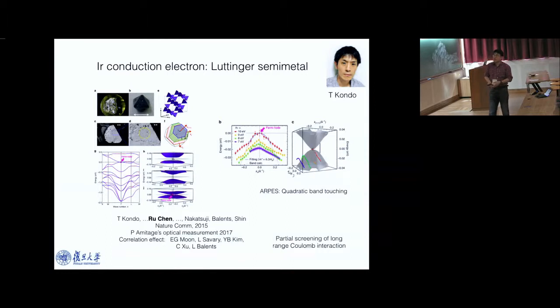So this is an example of a crystalline symmetry protected semimetal. The parent state of the conducting electron is this crystalline symmetry protected Luttinger semimetal. Yeah, so that's the ARPES result, the angle-resolved photoemission measurement. They found this quadratic band touching at the gamma point.